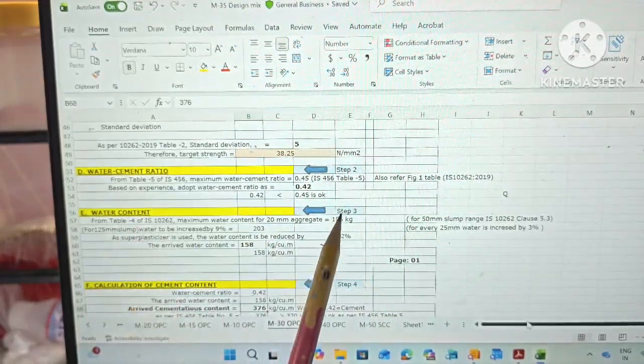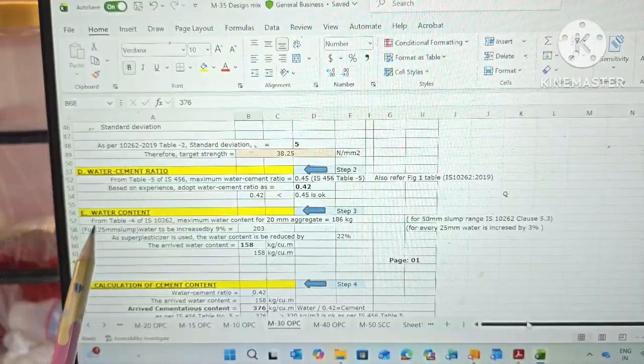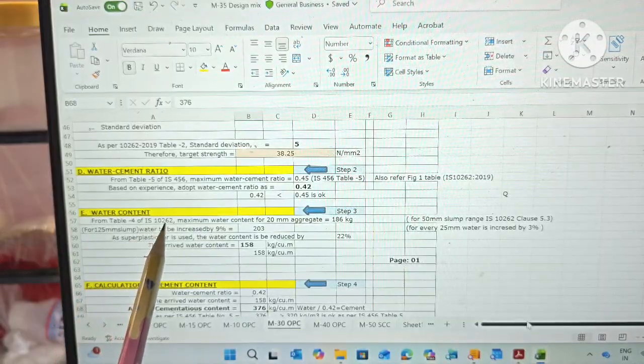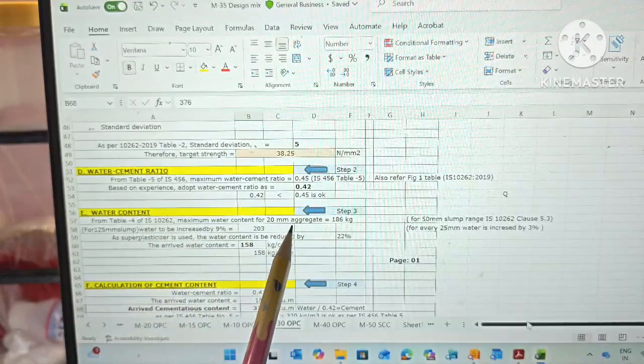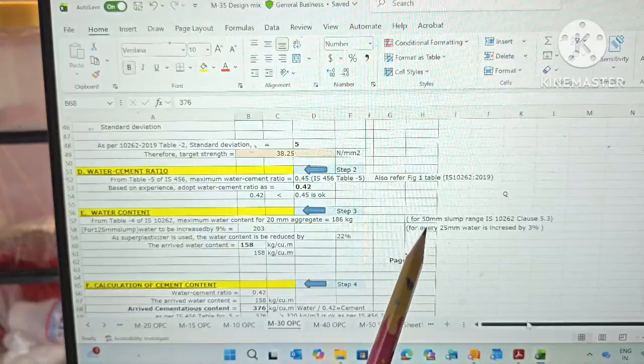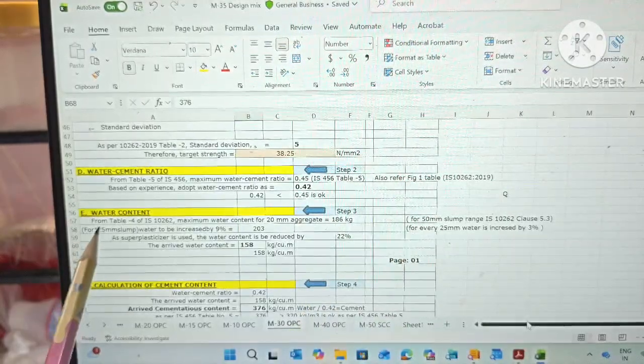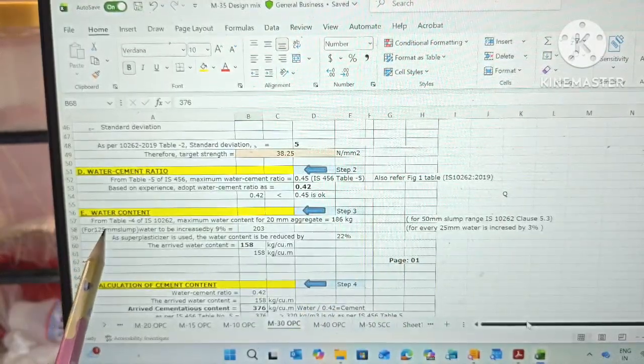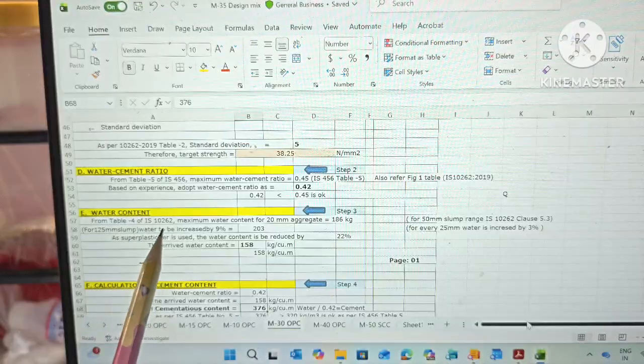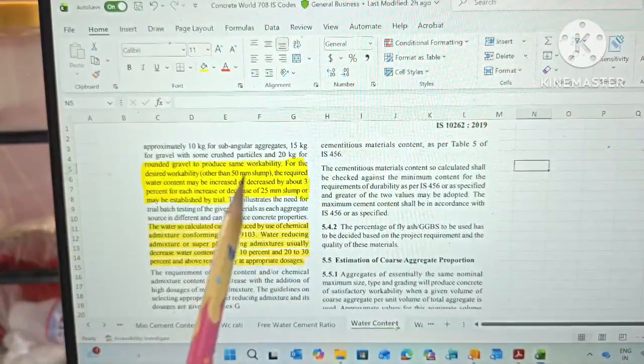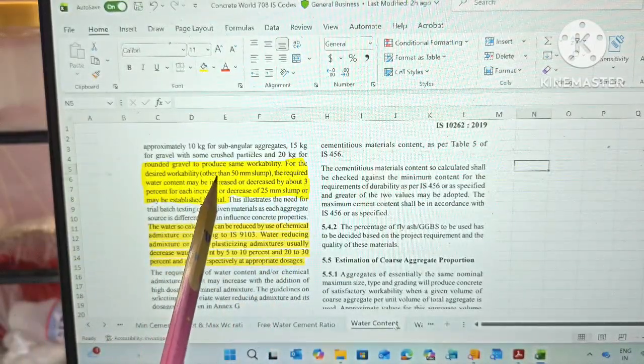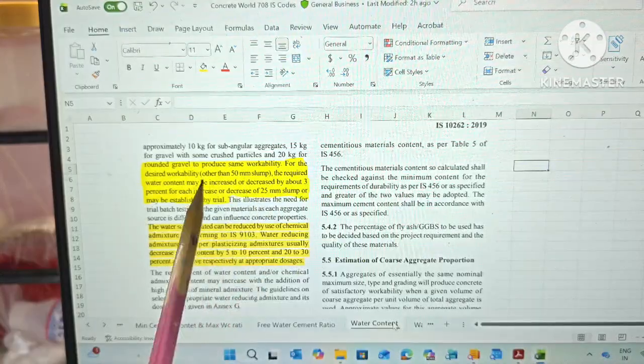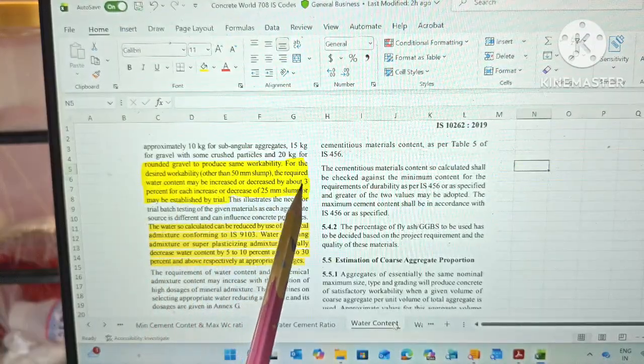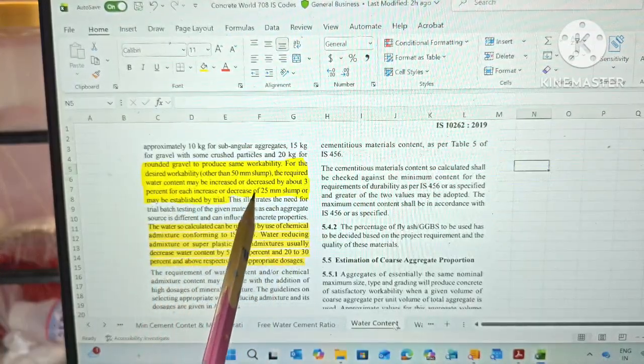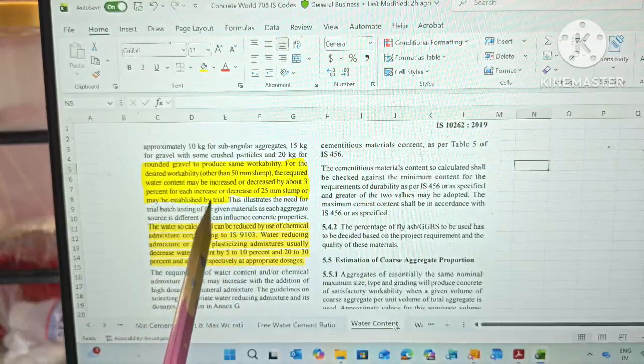Now moving on to step number 3, that is water content. Friends, from Table 4 of IS 10262, the maximum water content for 20 mm aggregate is 186 for 50 mm slump. But the slump required for us is 125 mm, that is 75 mm more. So as per IS 10262, for the desired workability other than 50 mm slump, the required water content may be increased or decreased by about 3% for each increase or decrease of 25 mm slump, or may be established by trial.